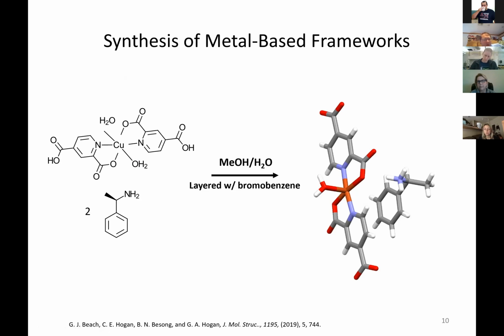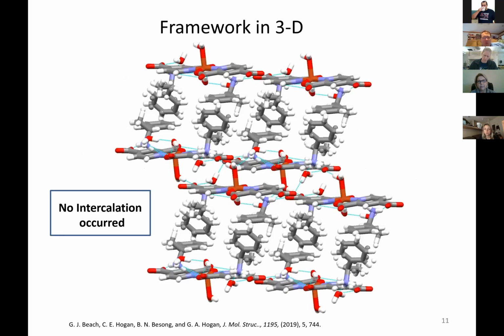Okay, it looks great. But the problem is this is just the unit cell. So again, we need to look at it and grow it in 3 dimensions. And once we do, we find we have a layered structure. Here's our metal complex forming a layer right here at the top, where you see my mouse moving. Here's one of our interlayer regions. And here's the bottom portion of our layer.